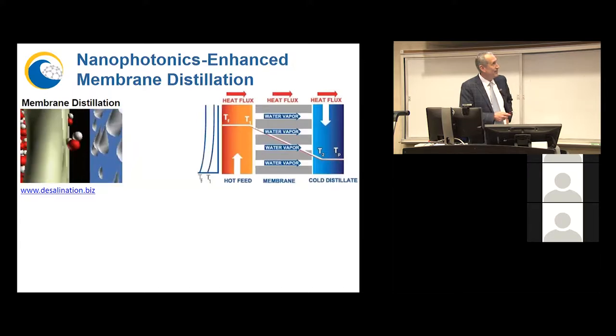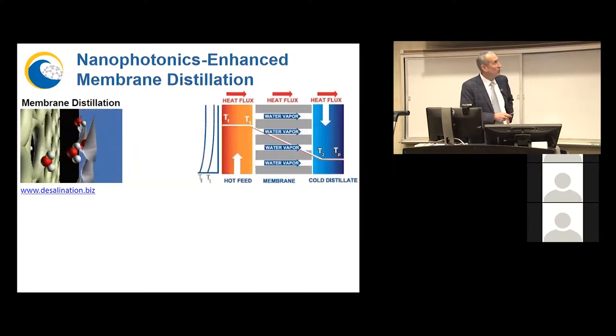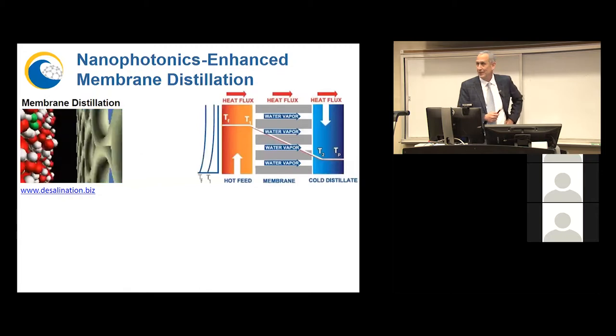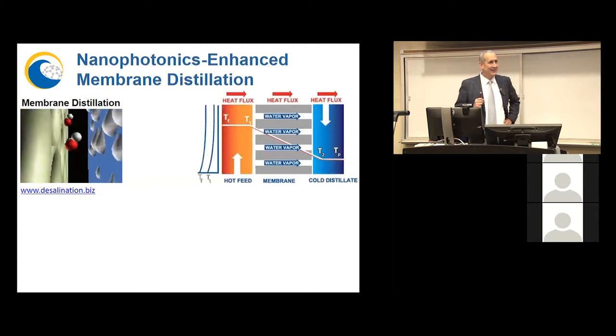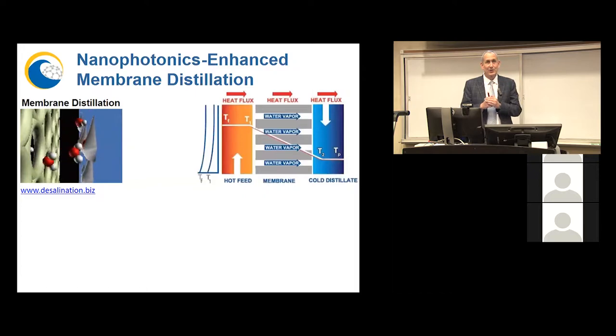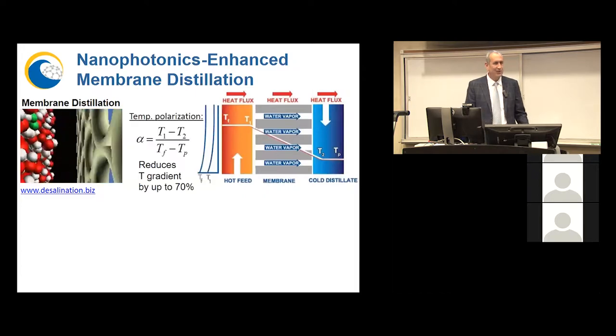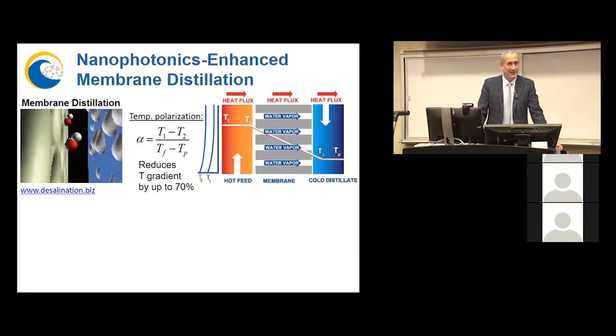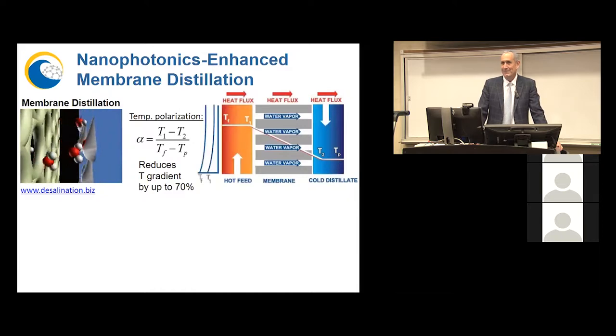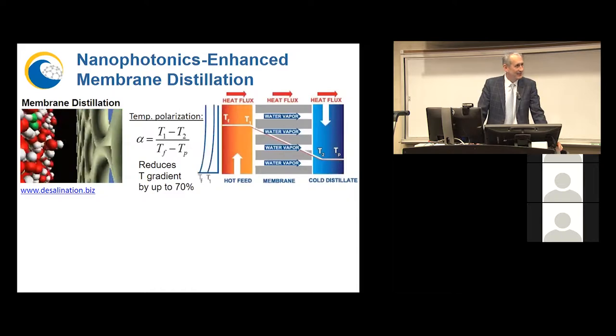The temperature of the water cools down at the interface with the membrane. That decreases the temperature gradient and decreases the flux. This is something called temperature polarization. And you can lose 70% of the flux due to this phenomenon.